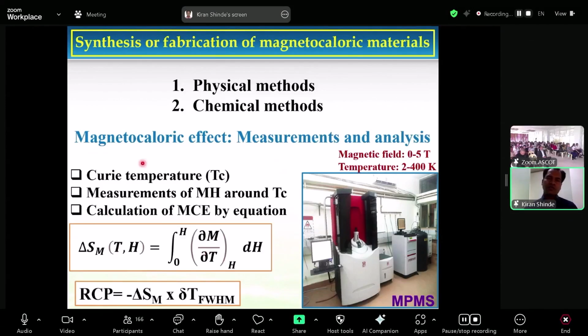So after the fabrication of the magnetic material or magnetocaloric material, we have to use the magnetic property measurement system, MPMS, or physical property measurement system. Using that equipment, we can measure the Curie temperature of the material. Then we have to measure the MH around TC, like before and after TC, and we have to use this theoretical equation to analyze the magnetocaloric material.